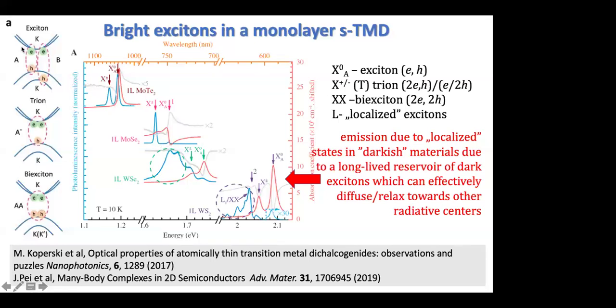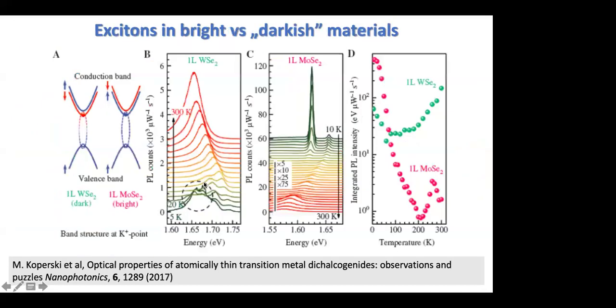Neutral exciton is a complex of electron and hole. Trion, two electrons and a hole, if trion is meeting. While the spectrum of tungsten material is composed of the very broad feature here, which is related to so-called localized states. Apparently, the story behind this is also very interesting, but still the spectrum looks completely different. And why it is so? If we look at the energy structure in both cases, dark or darkish, how we call it now, or bright, as I told you, in the bright material, bright exciton has lower energy. In the darkish material, the lowest energy exciton does not recombine.